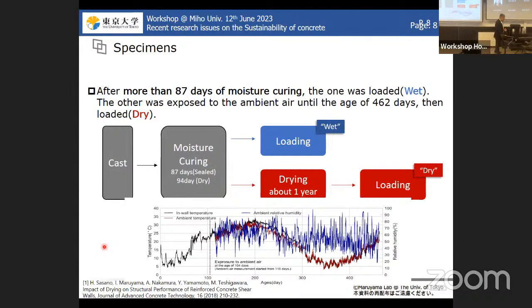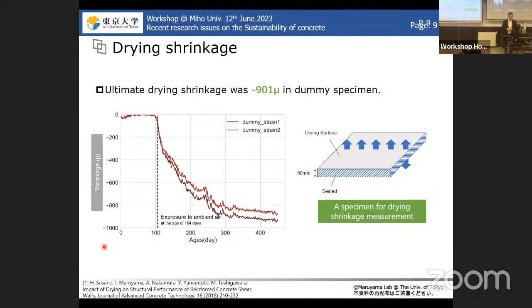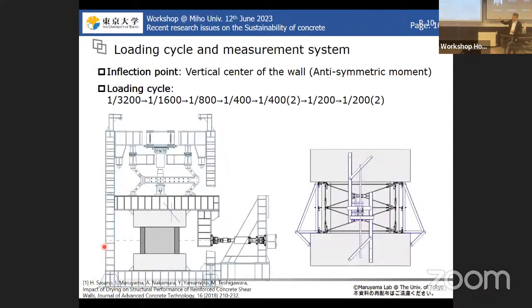I also prepared a dummy specimen, something like this, and measured the drying shrinkage of this specimen. It attained 900 microns, both horizontally and vertically. Then I loaded it using this kind of equipment, and we do cyclic loading to evaluate the performance of the reinforced concrete shear walls.